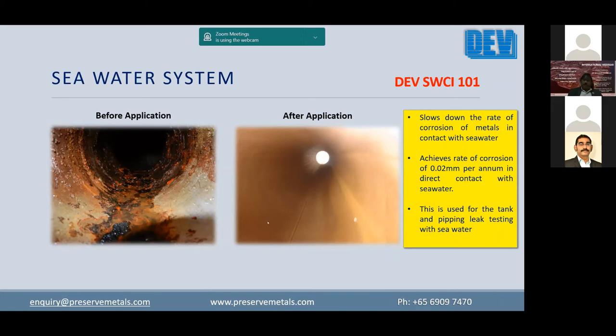In all such cases, the use of just 500 ppm of SWCI 101, which is a very cost-effective solution, will ensure that corrosion never happens. It reduces the rate of corrosion drastically, to just 0.02 mm per year. That means it forms a monomer protective layer between the seawater and the parent metal, and thereby decelerates the corrosion.